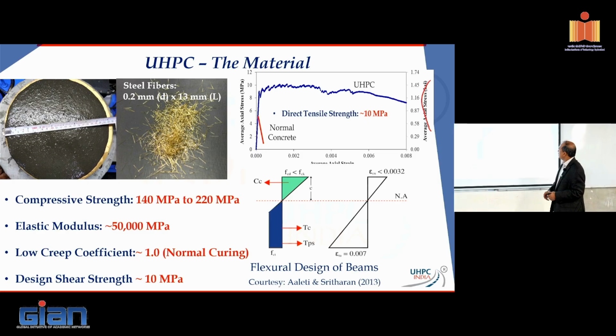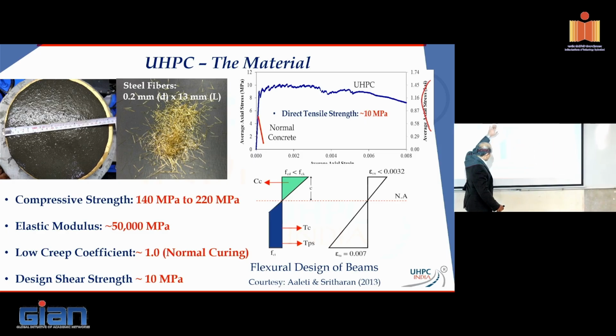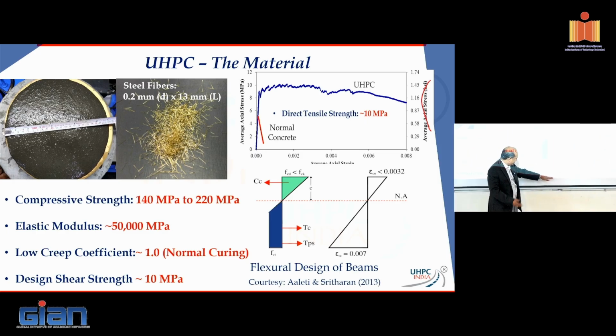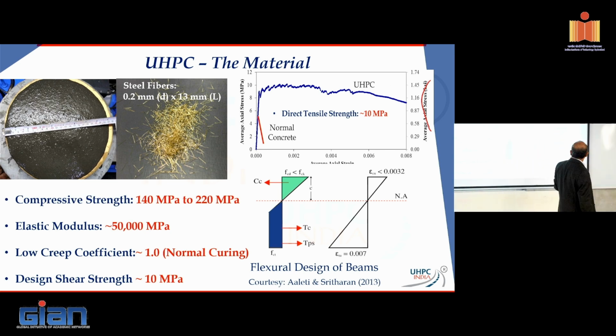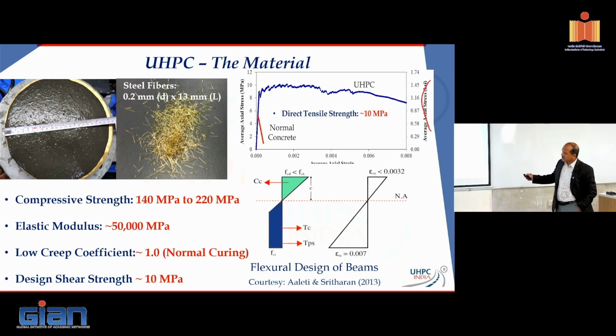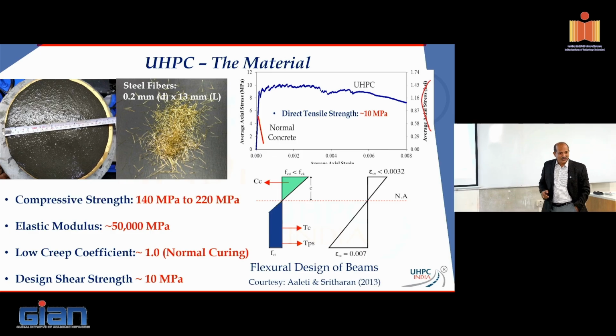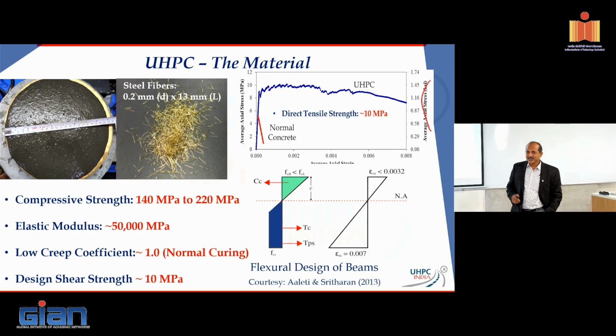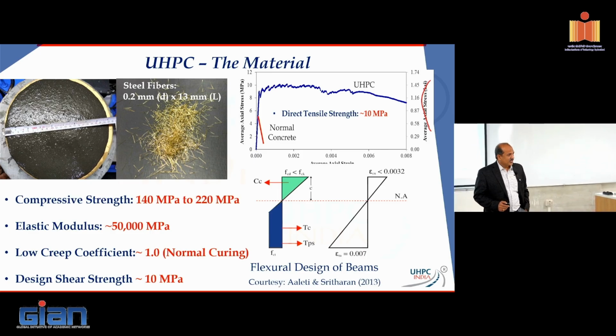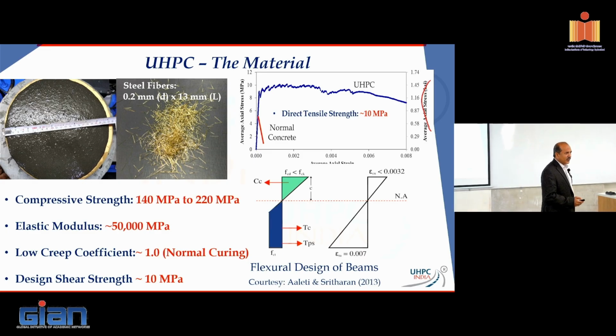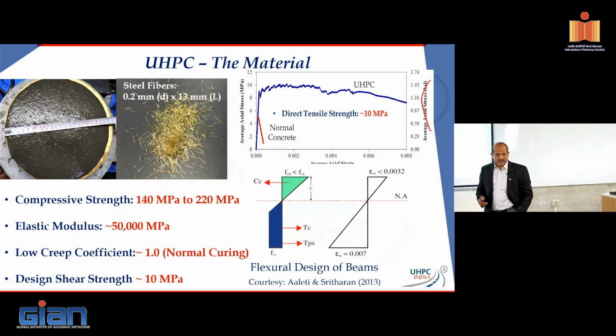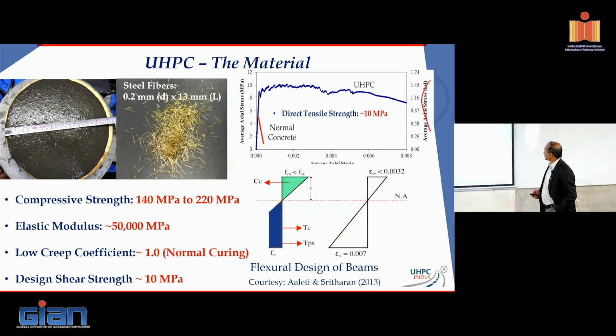So, yeah, that is something borrowed from a paper from Aaleti and Professor Sritharan right over here. But big difference. We saw this. Those are the steel fibers. They're brass coated in nature, about 0.2 millimeters in diameter, and generally 13 mm, but we are seeing some 20 mm work also being done in our country right now. So somewhere in between 13 mm and 20 mm.